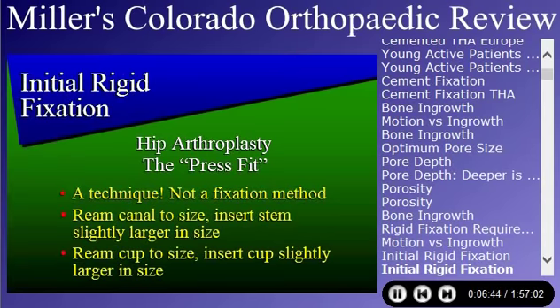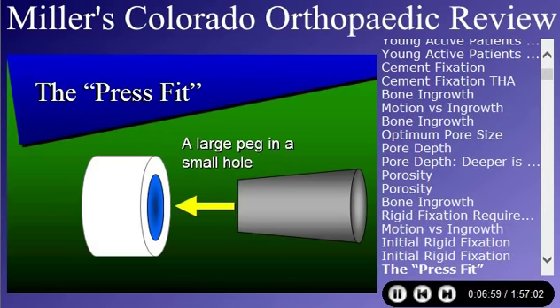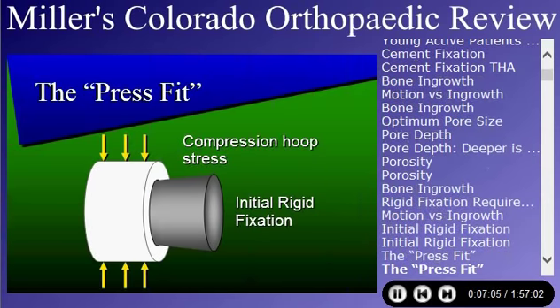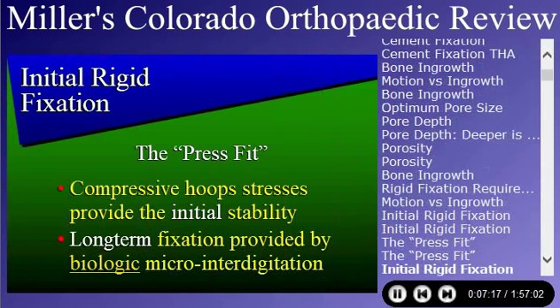What you really do is you ream the canal to a certain size, for example, 10 millimeters, and you insert a stem that's slightly larger, say, for example, 11 millimeters. Same thing on the cup. You ream to 50 millimeters on the cup, and you put in a 51 millimeter cup, slightly larger in size. The theory is that you're wedging a large peg in a small hole, and once it's wedged in, you generate these compression hoop stresses, and those initial compression stresses hold that implant in place for your initial rigid fixation so that the bone cells will grow into the porous coating. So the compressive hoop stresses provide the initial rigid stability for the first 6 to 8 weeks. The long-term fixation is provided by the biologic microinterdigitation, and that's the long-term survival of the prosthesis.